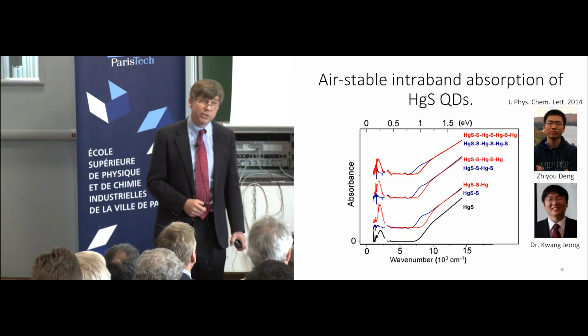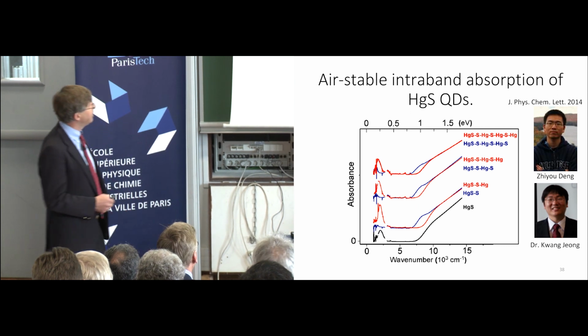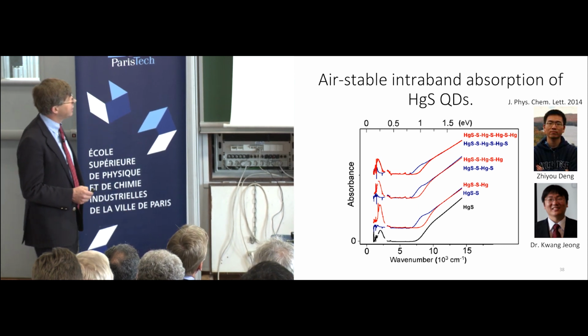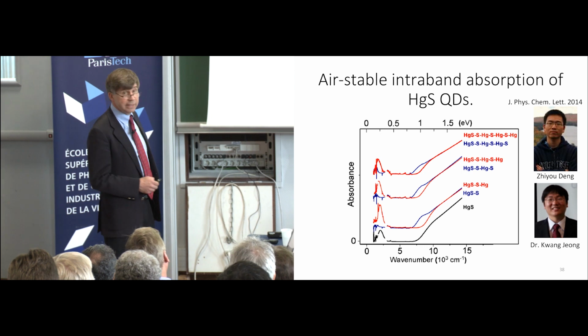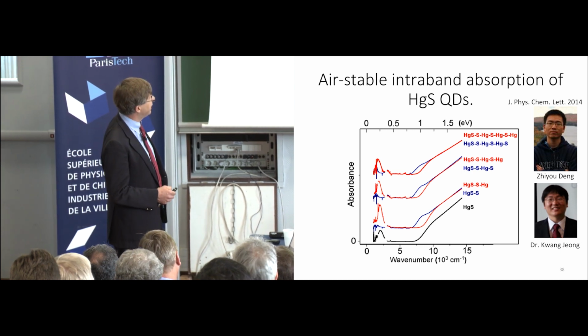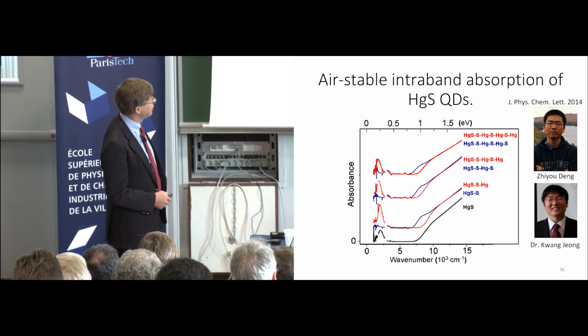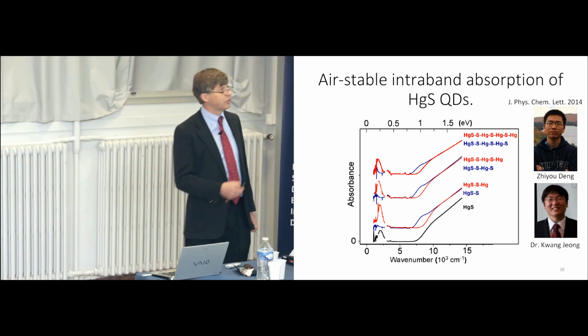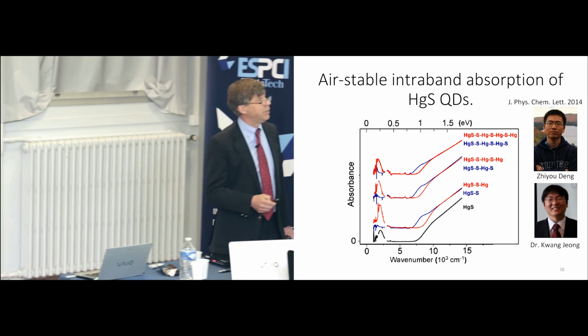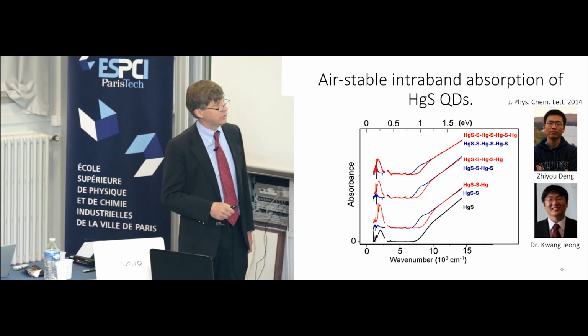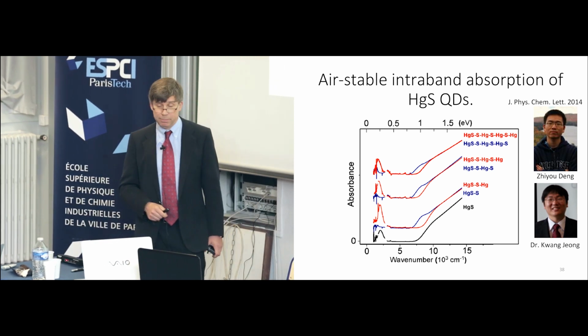The question was how to put 2 electrons in a dot. And we were lucky. We explored the other mercury chalcogenide. Mercury sulfide seems to do that by itself. You take mercury sulfide and you find this intraband absorption, and it's very sensitive to surface. So you can just dope it and undope it by putting mercury-rich or sulfur-rich on the surface, and we attribute that to a surface dipole effect.